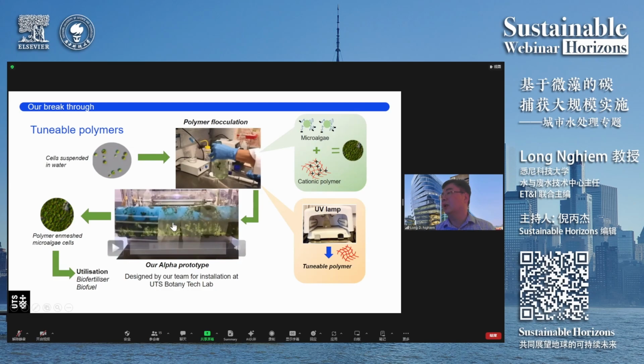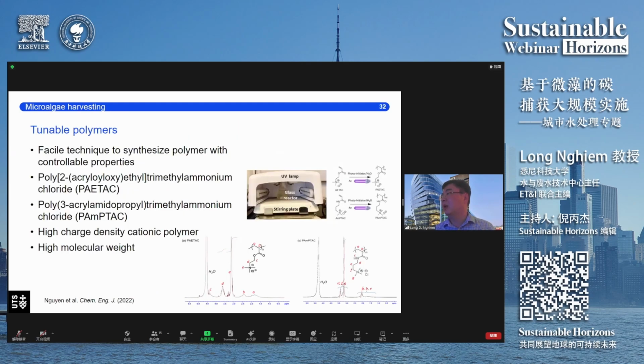Flotation, and then a conveyor belt to move it outside of the water solution. So how do we make the polymer? We basically use a photo-initiated polymerization process. So in the system, we have a photo initiator and a monomer. And when we radiate the solution of monomer with the photo initiator, we trigger the reaction chain of polymerization, and then we can form the polymer.